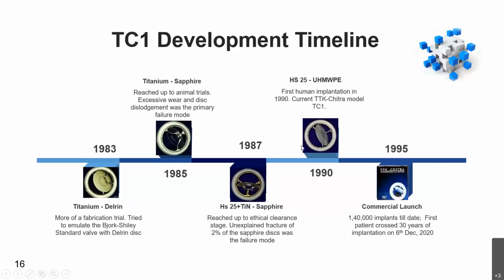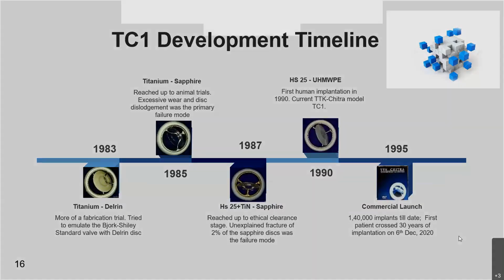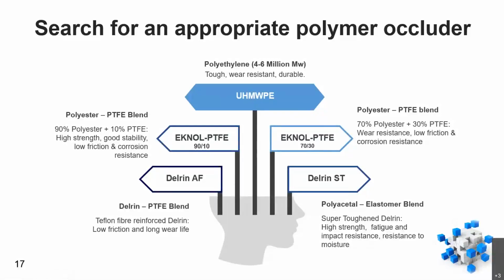Then a search for an alternative material for sapphire was started, and it took about another 3 years to come out with the currently available TTK Chitra valve. It has the same Haynes 25 cobalt-based alloy frame and ultra high molecular weight polyethylene. It's a polyethylene with a molecular weight in the range of 4 to 6 million Dalton. This particular model went through all the qualifications, and it reached the clinic in 1990. And in 1995, the product was launched commercially.